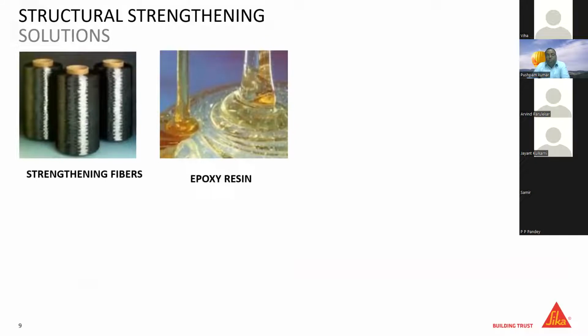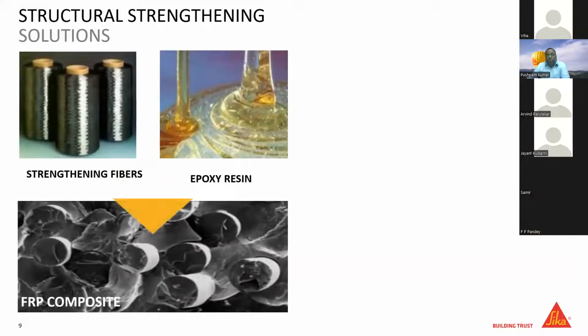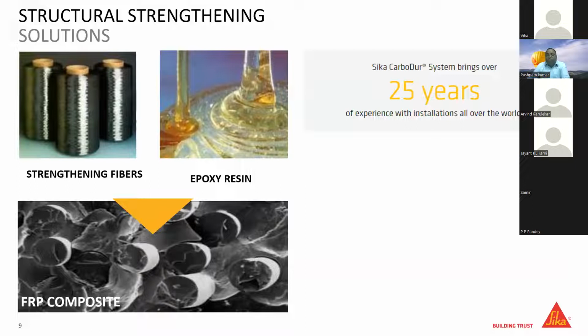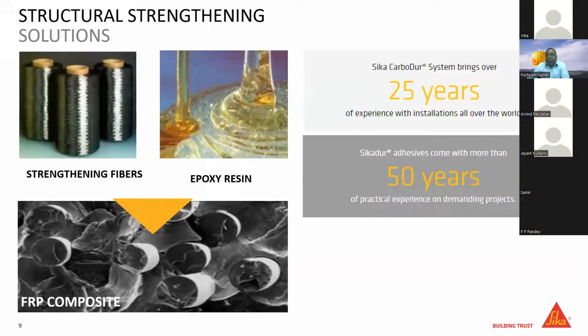What happens when this carbon fiber is mixed with epoxy resin, it forms a composite material. And this composite material has very high mechanical properties for enhancing the overall load carrying capacity of any structural member. Sika has more than 25 years of working with CFRP across the globe, and on epoxy, Sika has been working more than 50 years, and various tests have already been conducted on the compatibility of CFRP and the epoxy and the interlaminar shear failure. These are very important aspects, as any general epoxy will not be suitable for CFRP application. The epoxy resin used for carbon fiber should have different mechanical properties, should have high glass transition temperature so that it is compatible with CFRP application.